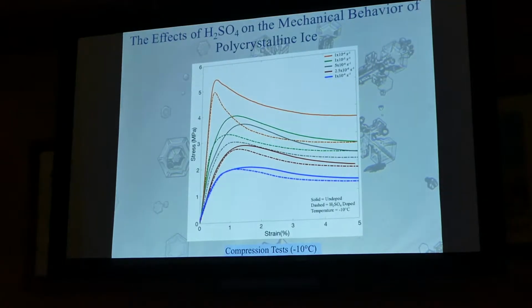So just jumping to some of the results here. These are the results from the compression tests at 5 different strain rates. I told you sometimes it'd be 1 hour to 5% strain, sometimes it'd be 13 hours to 5% strain. What you see initially as you put on the load is that the solid line here is the pure water samples, and the dashed lines are the ones that have been doped with sulfuric acid. And what you see is a difference in the peak strength. So this peak is higher than this one. Just that little bit of sulfuric acid added actually made the ice weaker.